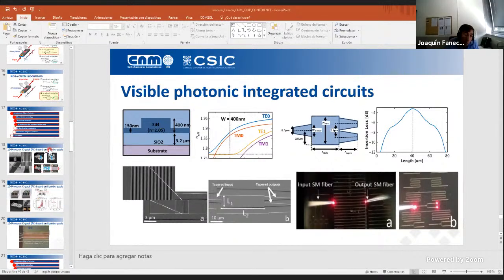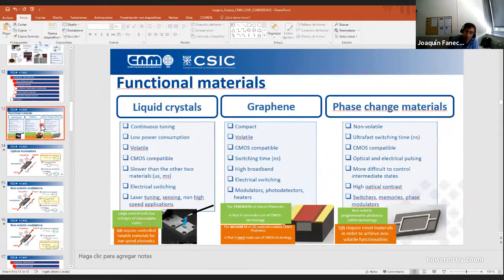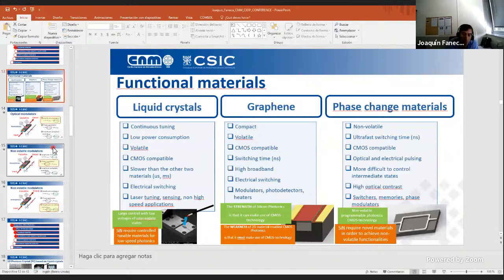Yeah, some companies do it, but to be honest, it's in-house. The thing is, it's not an easy thing to integrate. First of all, when you integrate it with the silicon, you need to take into account the position of the molecules when they touch the walls of the silicon. Normally, when you deposit the liquid crystal with a microneedle and flow it, the flow determines the positions of the molecules. At the same time, the ones near the walls, because of the forces between the silicon and the liquid crystal, orientate themselves towards the polishing of the wall of the silicon. So if the silicon has been etched and has some direction in the crystal, you will have this directionality in the liquid crystal as well.